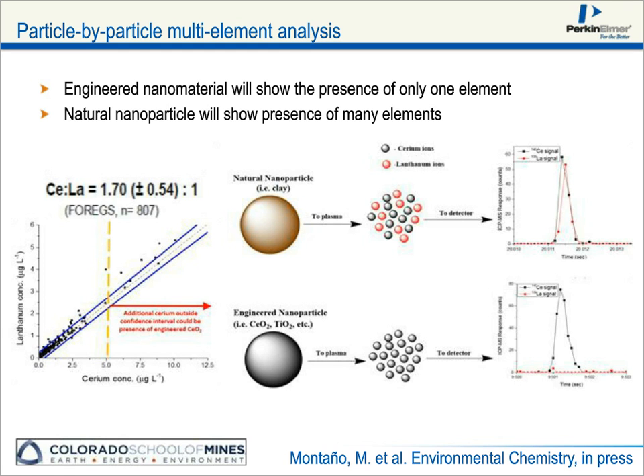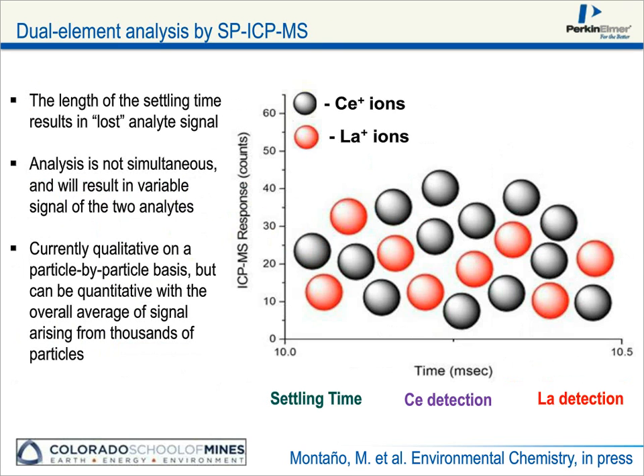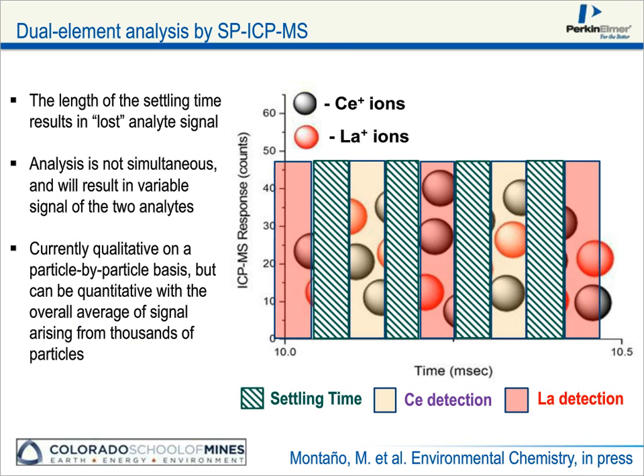So the way we might be able to do this, and I'm going to advance one more slide, is think about now by reducing our dwell time to on the order of 0.1 millisecond, we might be able to detect both cerium and lanthanum particles as they enter the plasma. Of course, we have some missing data. We have the settling time, which hopefully we can keep quite short, that we have between our first ion and our second. So there's a bit of data loss, and we have to deal with that.